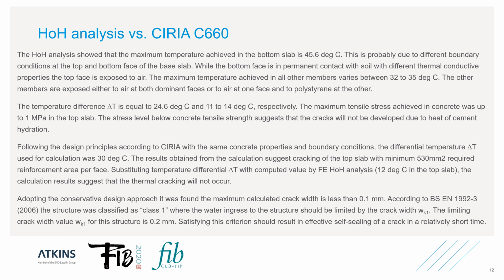Following the design principles according to CIRIA with the same concrete properties and boundary conditions, the differential temperature delta T used for calculation was 30 degrees Celsius. The results obtained from the calculations suggest cracking of the top slab with minimum 530 mm² required reinforcement area per face. Substituting temperature differential delta T with the value computed by FE HOH analysis, the calculation results suggest that thermal cracking will not occur. Adopting the conservative design approach, it was found that the maximum calculated crack width is less than 0.1 mm.